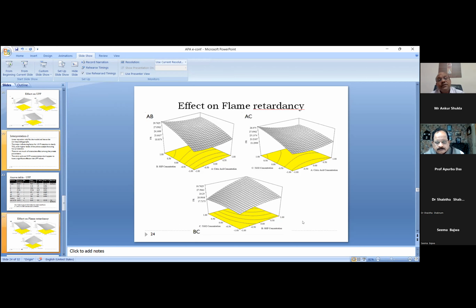Then moving to the last one, that is the effect of flame retardancy. So here again, if you go to the first one, you find that as we are increasing SHP, that is the sodium hypophosphite concentration, the flame retardancy is significantly increasing. And for obvious reasons, because the phosphorus retention will be more if you have more of SHP, because more of addition reaction will take place between the cellulose, which is again linked to the polycarboxylic acid, and hence the phosphorus content is high, and probably that is contributing to higher flame retardancy.